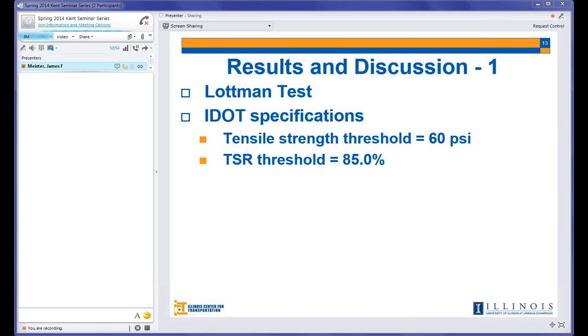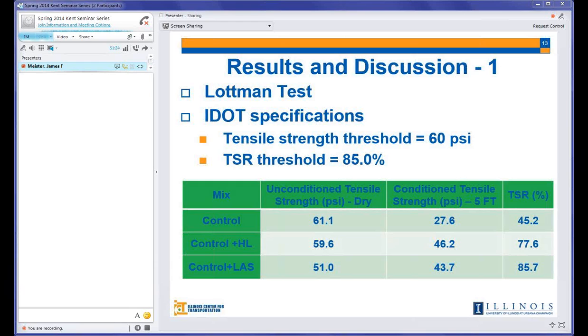The tensile strength threshold for unmodified mixes, which is our case because we use PG64-22 unmodified binder, is 60 psi. Lower than 60 psi means that the mix is weak. The TSR threshold, the tensile strength ratio, is 85%. So if your mix has a TSR less than 85%, this means that it is a moisture susceptible mix. Going to the results, in this table we have the results for the 3 mixes.